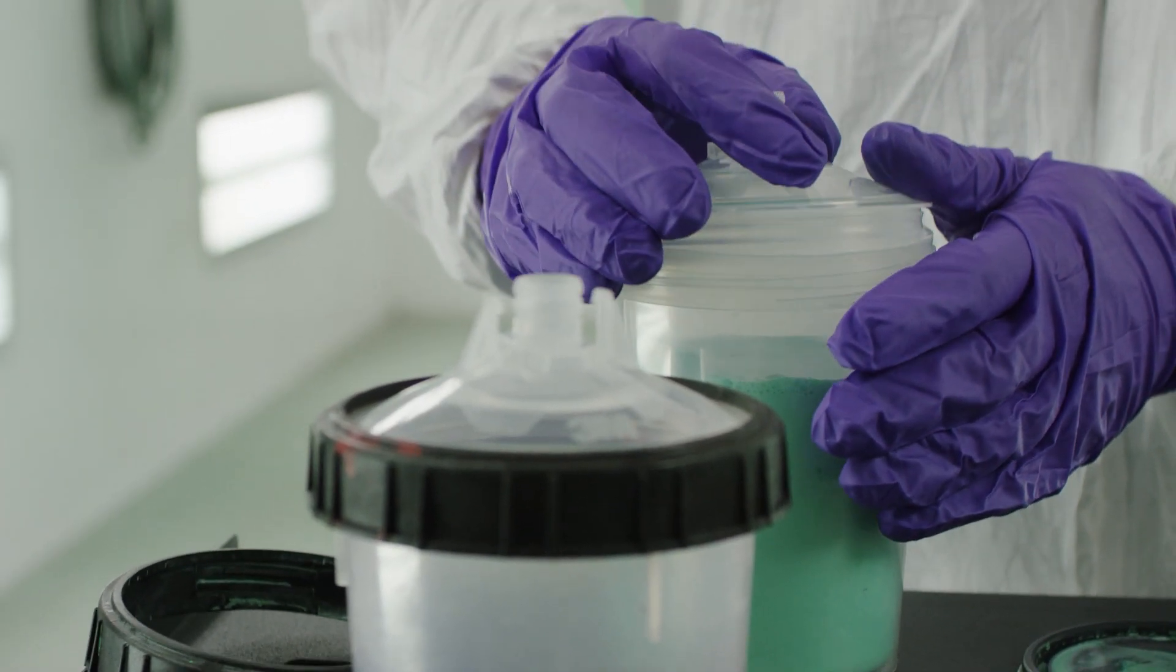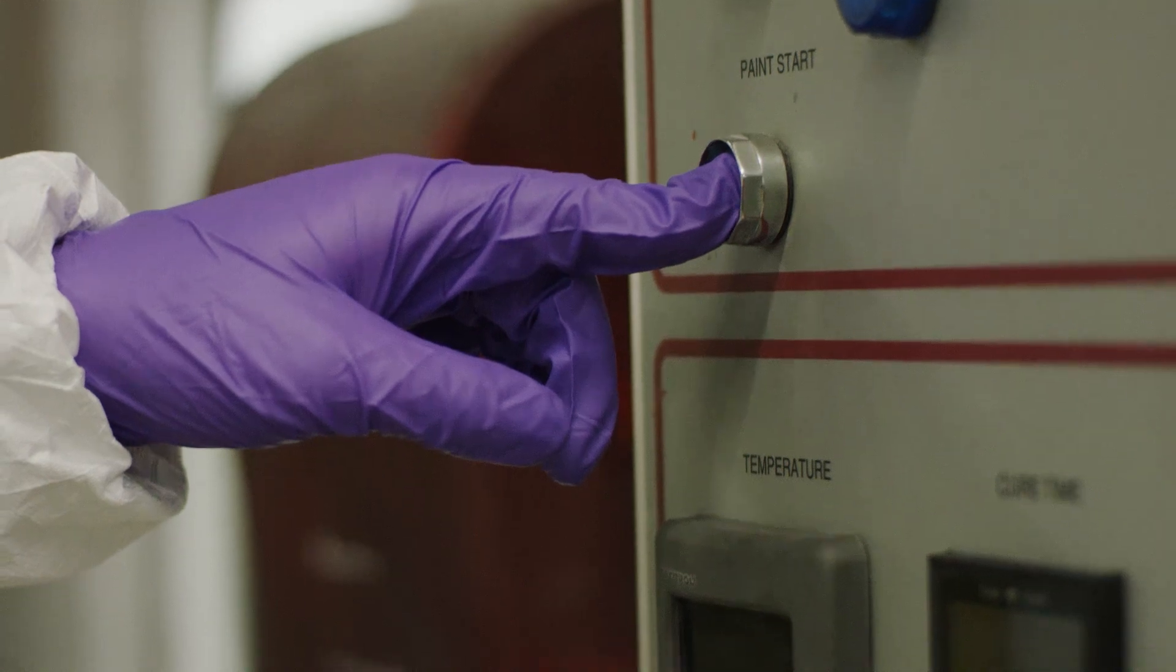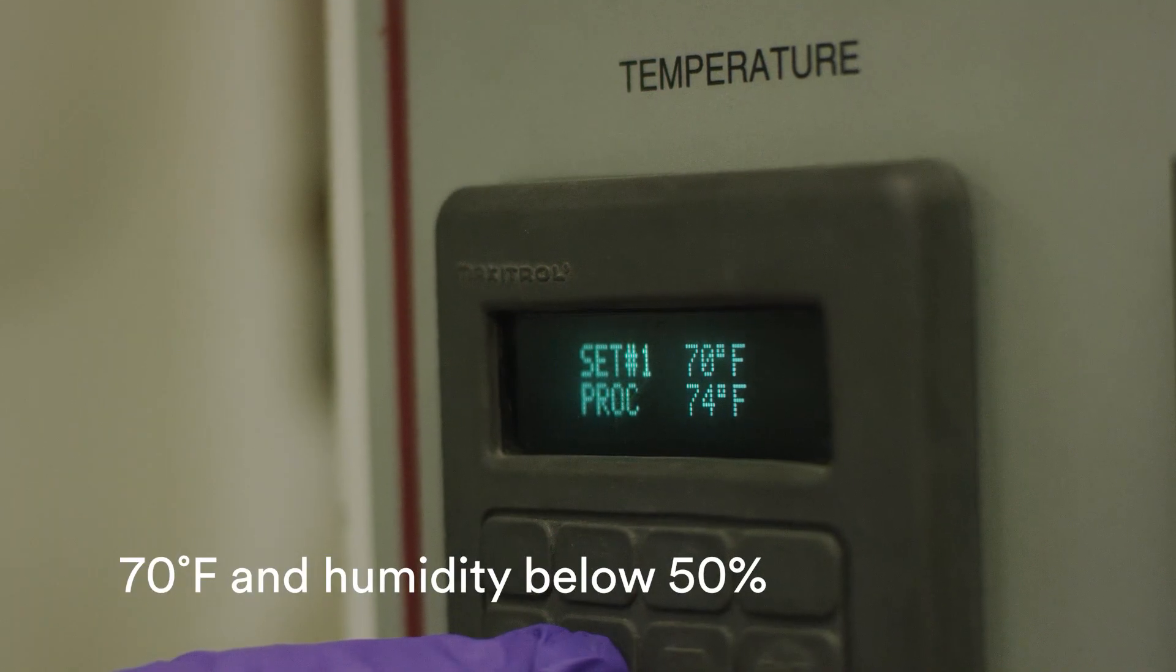The spray of water-based products varies with temperature and humidity. For optimal appearance, the booth temperature should be above 70 degrees Fahrenheit and humidity below 50%.